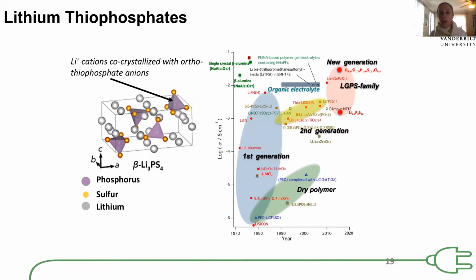Over the last couple of years, we've been working on lithium thiophosphates, which are sulfides. Sulfides are great because there's a lot of push toward using them: they have very high ionic conductivity, they don't require the high pressure processing that garnet oxides have, and they are pretty easy to synthesize. That being said, they do have air stability and water stability challenges, and they potentially require a larger infrastructure for manufacturing. Larger scale questions are still being answered at present.